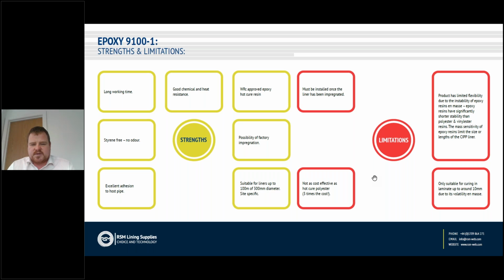It's particularly good for areas where you've got high levels of hydrogen sulfide attack. One further limitation is the ability to impregnate and laminate epoxy in larger thickness or en masse. Epoxy is a volatile material when you are mixing it in great volumes, and so we should be careful to process it in as smaller volumes as possible and ensure that we are curing according to the manufacturer's recommendations.